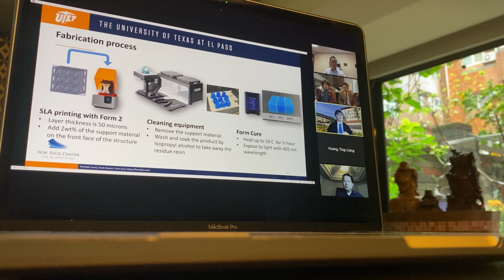After printing, we remove the product from the build plate and remove the support material with this tool. After that, we wash and soak it in a solution, isopropyl alcohol, for 20 minutes to get rid of the resin from the product. After cleaning, we use a curing machine to post-cure the product at 50 degrees Celsius and expose the product under light with a 405 nanometer wavelength for half an hour to make sure the product is totally solidified.